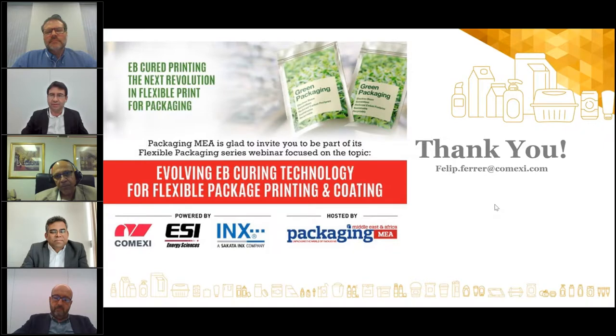We can print a wide range of materials and films. Already mentioned were polyethylene, polypropylene, polyester. In the case of polyester, we recommend chemically treated polyesters for better bond strength and adhesion. Foil can also be printed, but will require a primer or a primed white. The offset CI is a kind of hybrid combining offset and flexo UV, because offset applies a thinner layer of ink, and then for a high opacity white, or more grammage for a high gloss or high matte varnish, we use the flexo UV that can apply more grammage. But for all kinds of applications, we can provide solutions.